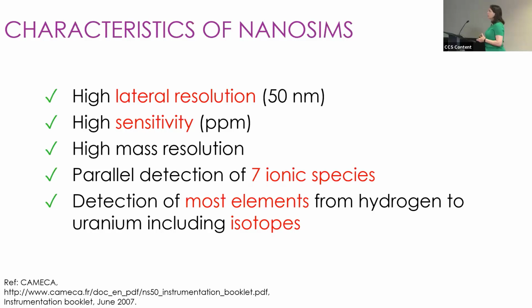There is also high mass resolution that allows us to distinguish between elemental species that have nominally the same mass. For example, sulfur has a mass of 32. Two oxygen atoms bonded together also have a mass of 32, but we can distinguish between them. That's really important when we're doing the isotope work that I'm going to show you today. We have 7 detectors, so we can simultaneously detect 7 ionic species. So we can co-locate our element of interest with something that tells us about the morphology of our sample, so we can know exactly where in the microstructure or any particular structure that element is located.